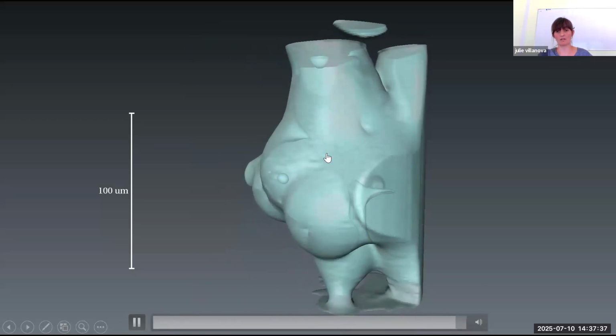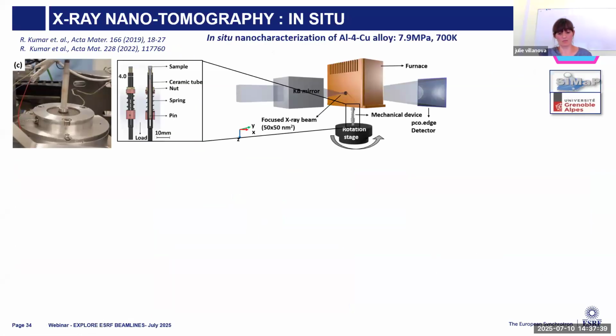curvature between the beads. So in this furnace, you can adapt some small devices. This is an example of the work of the PhD of Rishi Kumar, where a tensile device has been designed. So the sample is introduced in the tensile device, either in this version or in that version. It's mounted on the rotation stage, and then they are introducing it into the furnace. The sample in that case was aluminum copper. The furnace was at 430 degrees C.